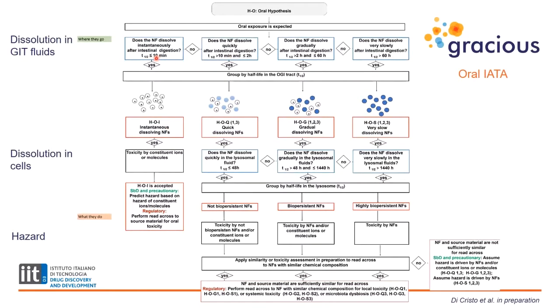So at this end here we have very quick dissolution rates, as indicated by a half-life of very short duration, through to more biopersistent, low solubility materials with a very high half-life. So first of all, we assess dissolution in the gastrointestinal fluids, and this allows us to decide whether our nanoform is instantaneously dissolving, quickly dissolving, gradual, or very slowly dissolving.